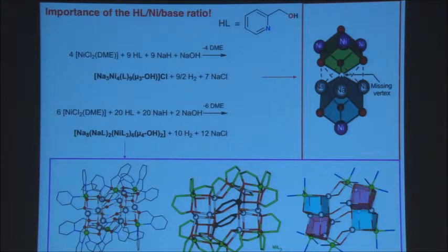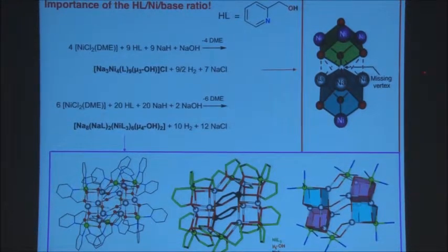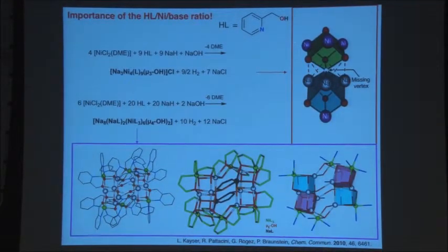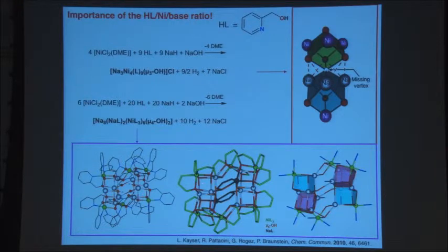And you can go on. I will not go into all the detail, but you can optimize eventually a synthesis to get to certain types, the one I have shown you before, with the sodium incorporated. By varying the ligand, the ratio, you can go to far more complicated structures, which I will not detail, which again contain sodium cation, nickel cations, hydroxide ligands. And here you can see this is the same compound, a nickel 6 sodium 10 cluster, which again can be analyzed in terms of cubane subunits linked to each other. And I think this is also, conceptually speaking, an interesting point that shows that these entities can be actually attached to each other to form superstructures, but all belonging to coordination chemistry, because we have metal-ligand interactions here, which are clearly coordinative bonds.